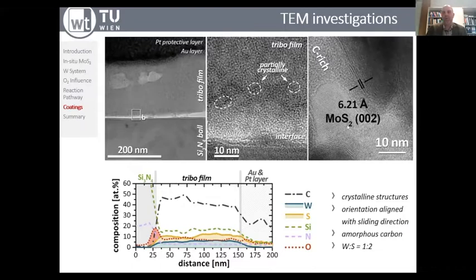In this case, I'm sorry, this is a typo, it should not be MoS2, it should be WS2, that we actually form the tungsten disulfide very locally in the tribofilm that is still mainly amorphous, but you have these growing islands of crystalline patches in the tribofilm. And one other prerequisite for a working tribofilm is that you have a very nice alignment alongside these lattice planes. And on the other hand, of course, as I said, the tungsten delivery and the oxidation process taking place before. So this is a very final proof that in this film, we actually found islands of tungsten disulfide that can be easily proven by the lattice spacing that we measured in TEM.